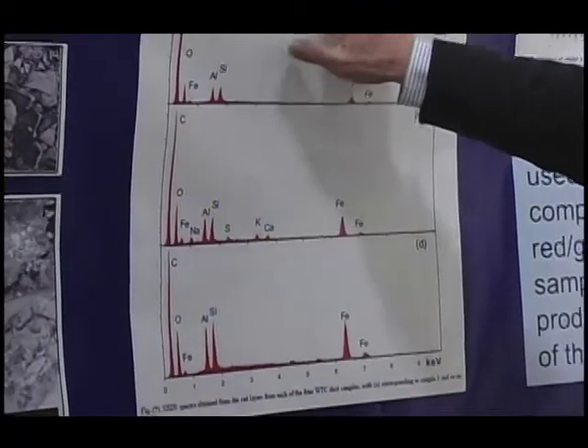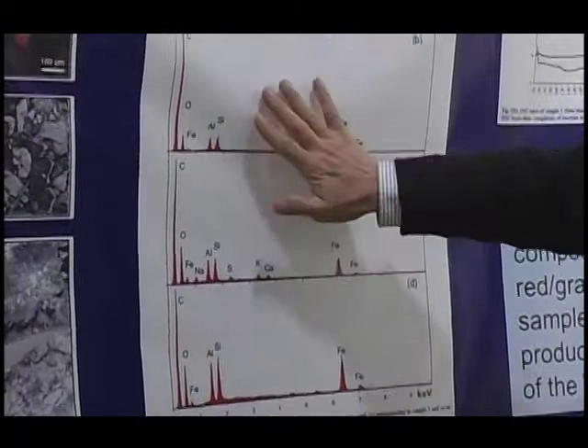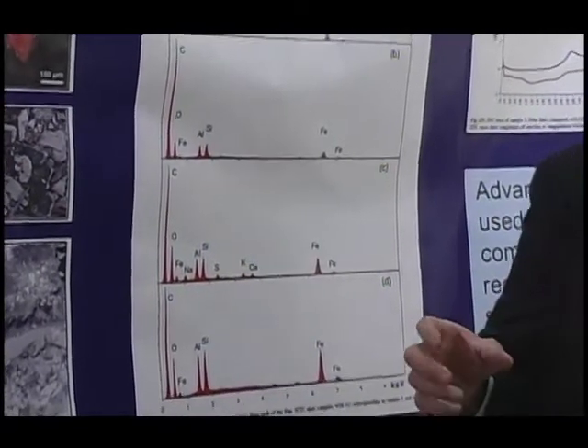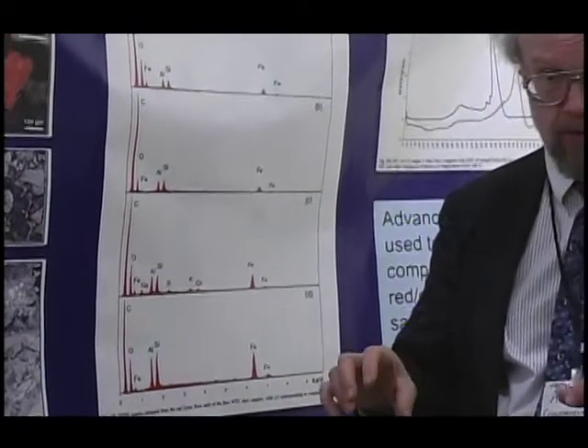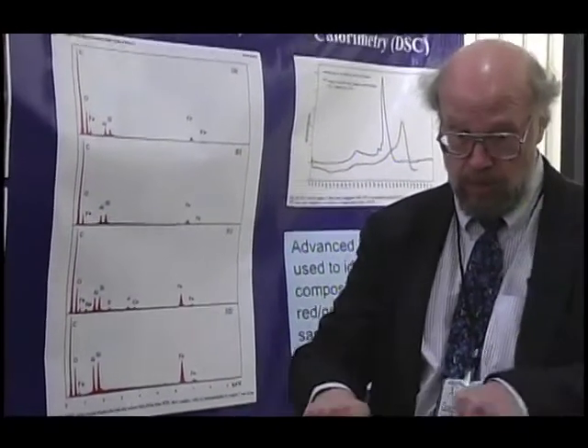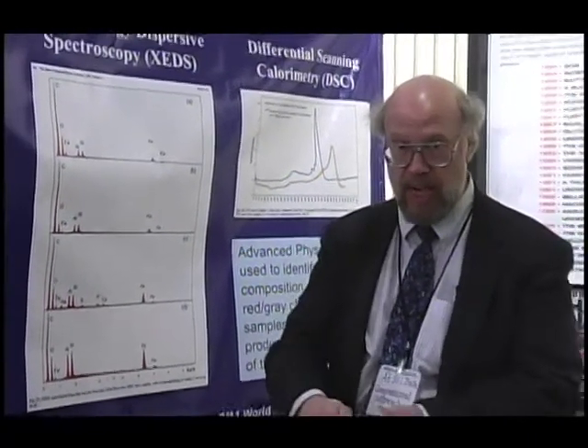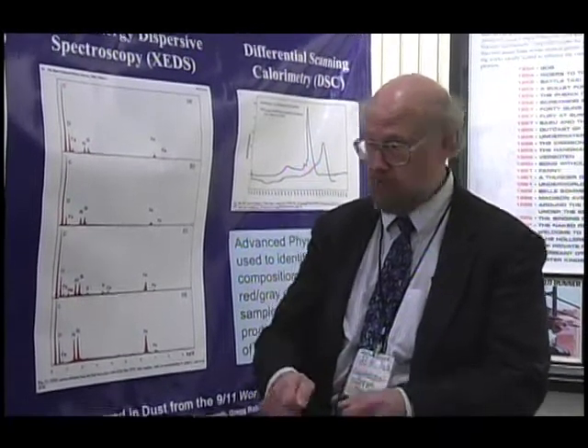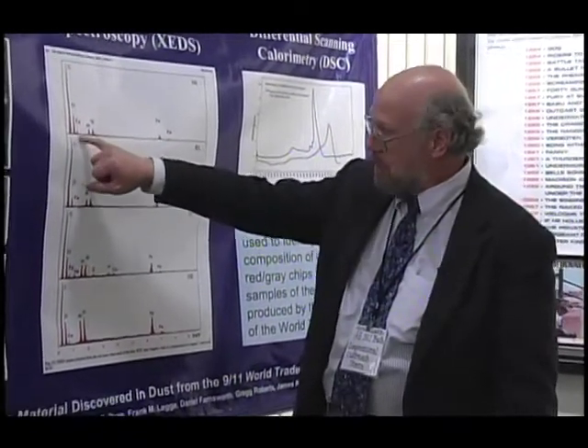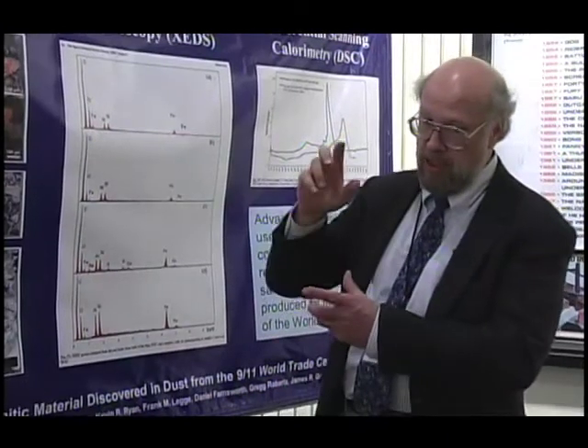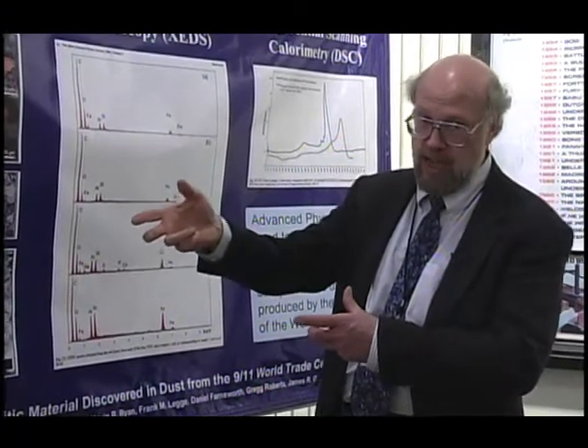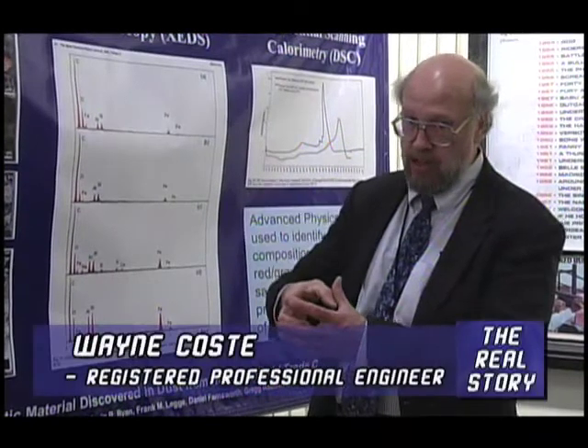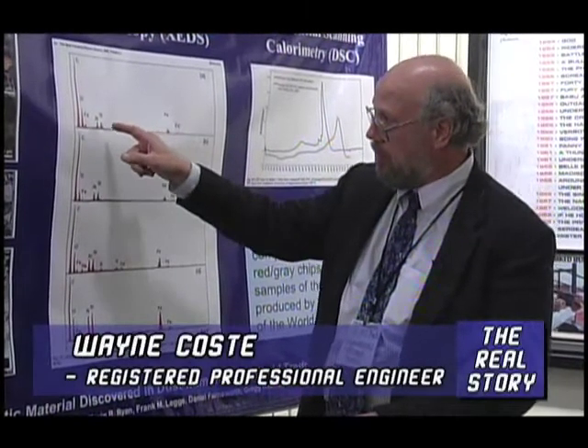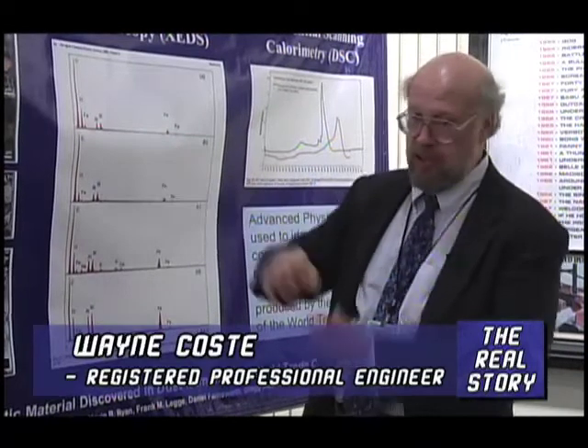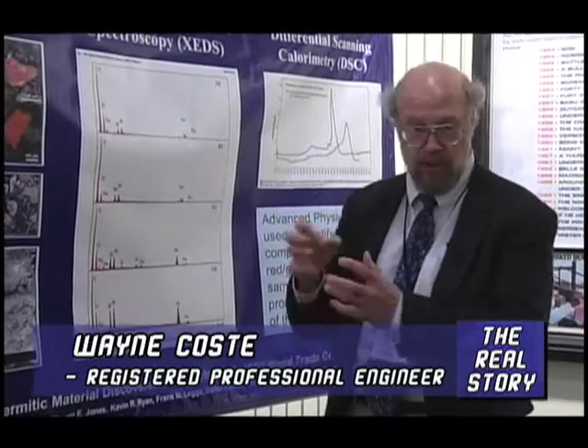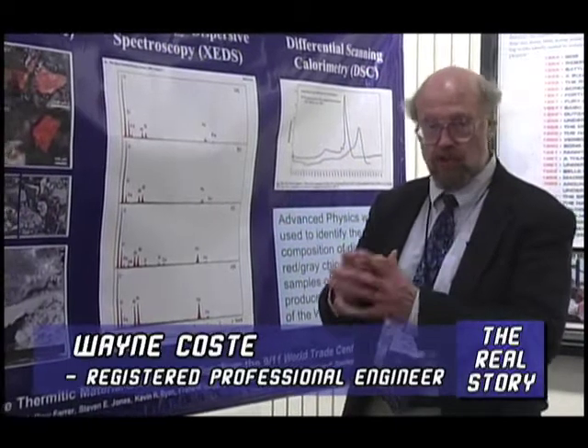And if you take a look at what thermite is, for example, it's what they use to CAD weld electric rails together, railroads, so you have continuously welded rail. You put the rails together, you put the powder there, you ignite it by heating it up, and once it starts to react, it's iron oxide and aluminum. You heat it up enough, the aluminum will grab the oxygen off of the iron oxide, leaving you with elemental iron, and the aluminum oxide is a white smoke that goes off, and so you have this reaction that creates iron, and the temperature of the iron will be about 4,500 degrees.